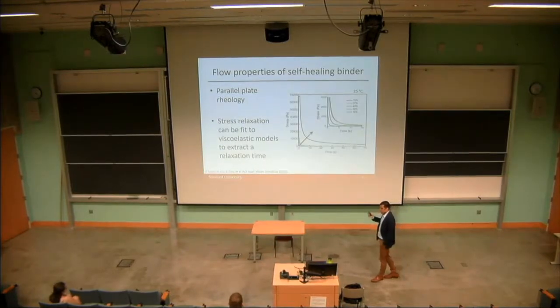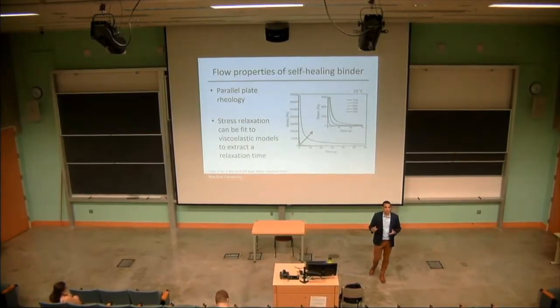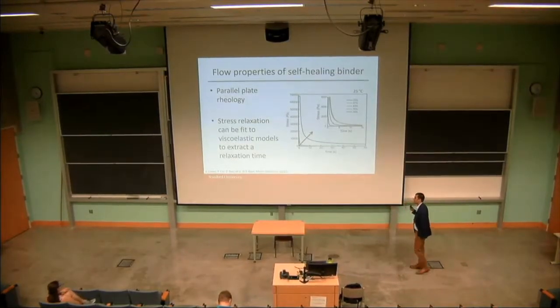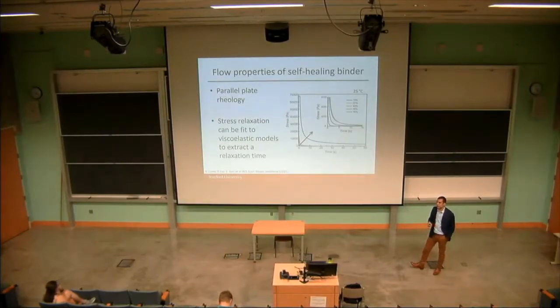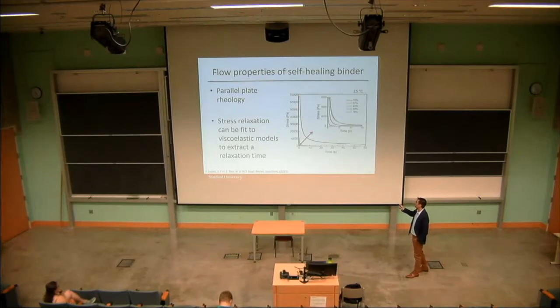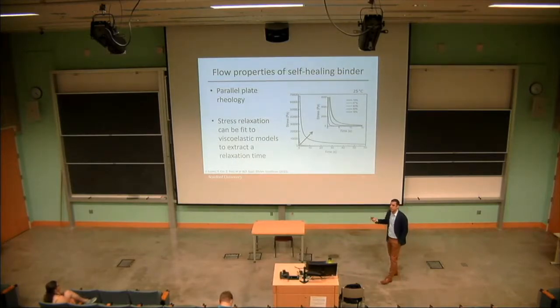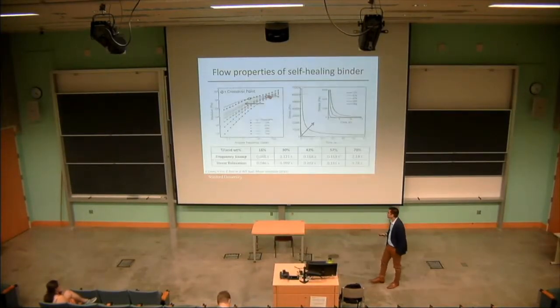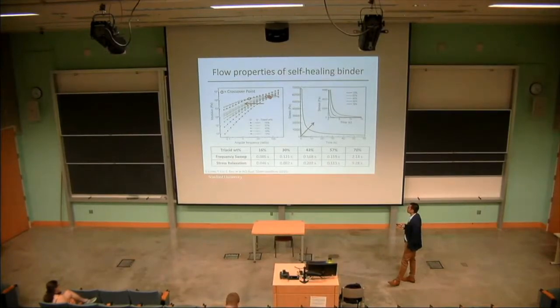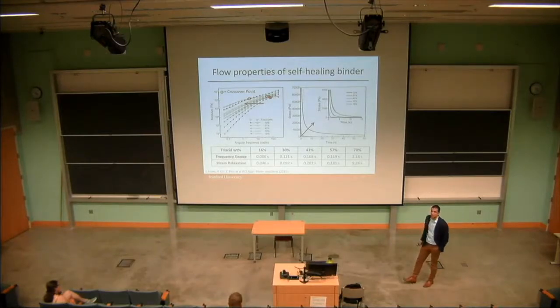We can also look at stress relaxation. So this, instead of oscillating, we just add a step strain and watch as the stress relaxes, and you can imagine that's really the flowing of the polymer material as it rearranges to relax the stress. And if it was some sort of elastic or structured material, it would maybe store some of that stress in some sort of structure. But here we see the stress is basically relaxing completely, and we can fit this relaxation to some viscoelastic models and extract a characteristic relaxation time. And what that allows us to do is, again, see what time scale these polymer chains are moving around and what time scale these hydrogen bonds are rearranging. So when we look at a comparison between these two methods, we see quite good agreement between the two, and then we also see that we have about 2 orders of magnitude of time scale that we're probing here.